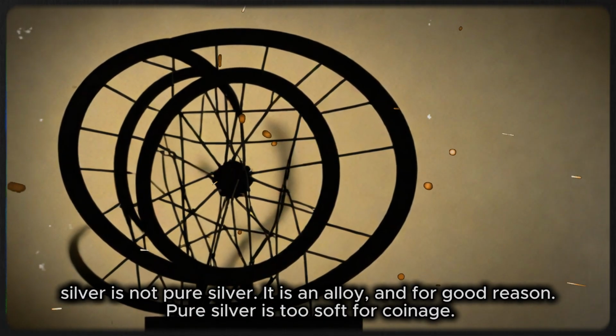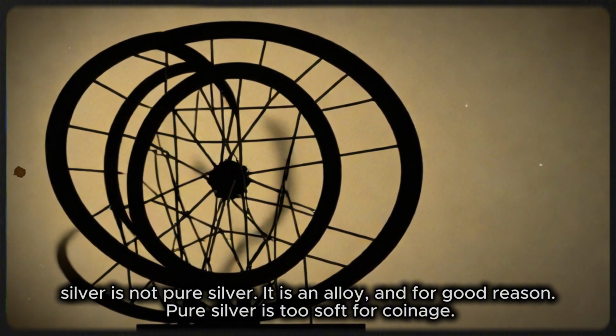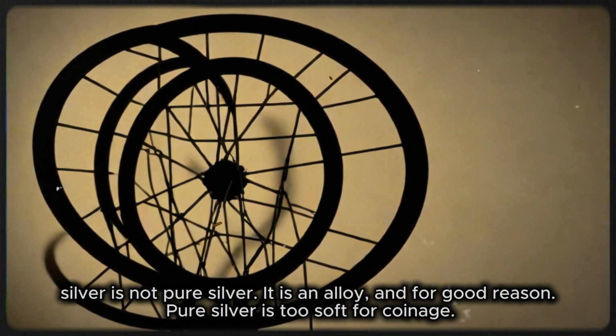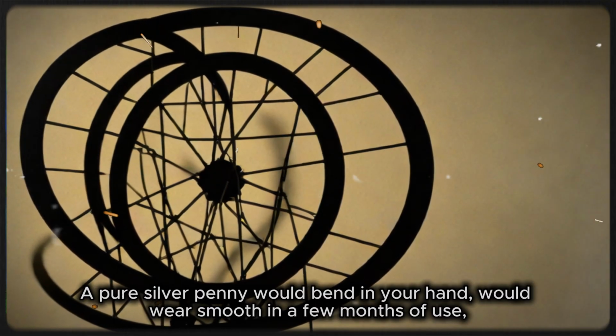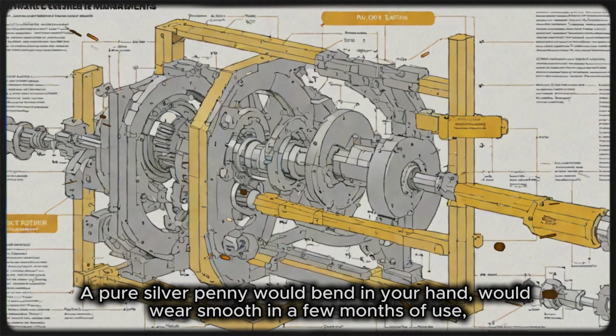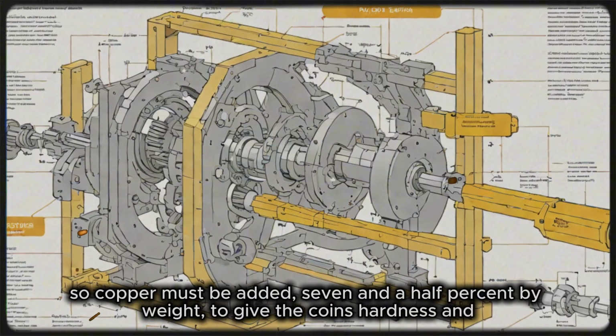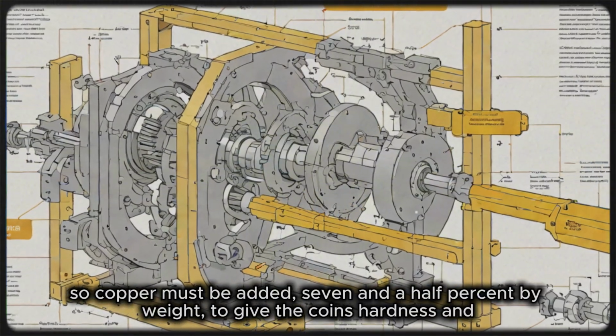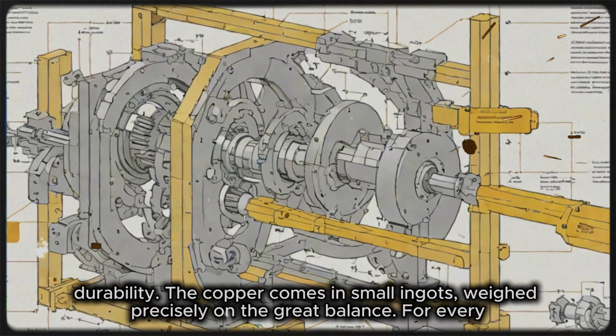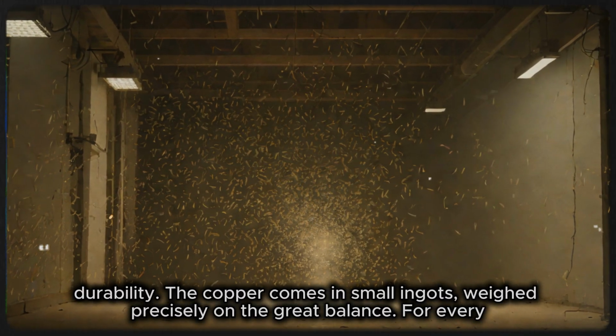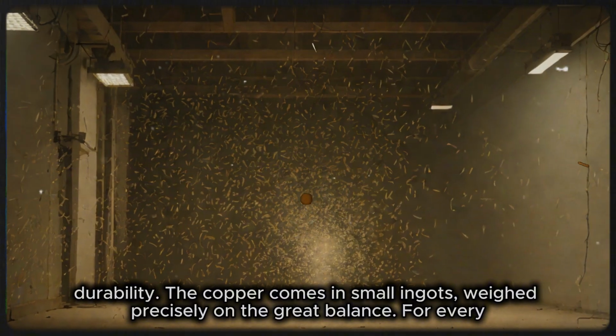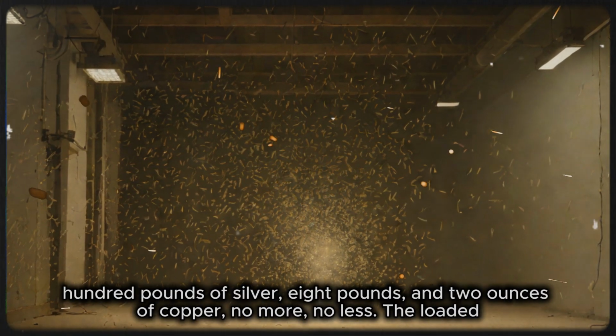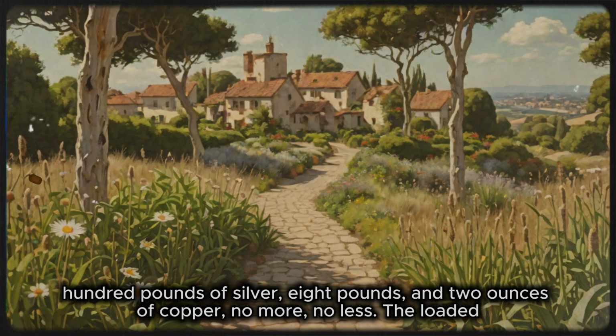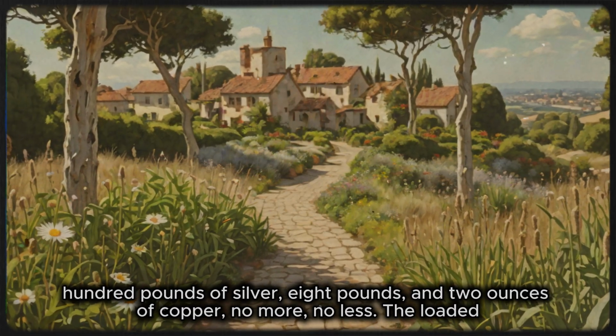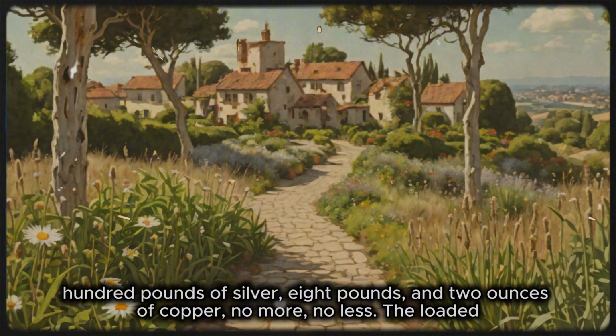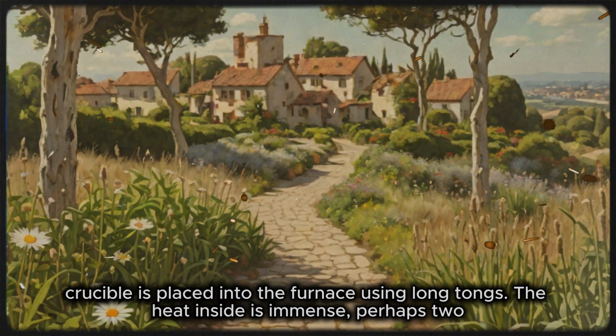But sterling silver is not pure silver. It is an alloy, and for good reason. Pure silver is too soft for coinage. A pure silver penny would bend in your hand, would wear smooth in a few months of use. So copper must be added, 7.5% by weight, to give the coins hardness and durability. The copper comes in small ingots, weighed precisely on the great balance. For every 100 pounds of silver, 8 pounds and 2 ounces of copper. No more, no less. The loaded crucible is placed into the furnace using long tongs.